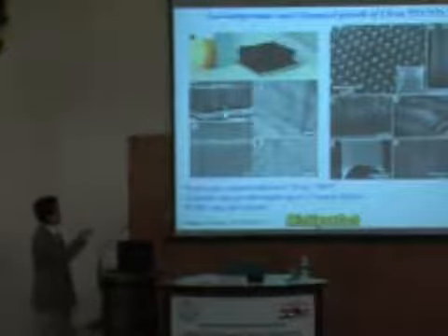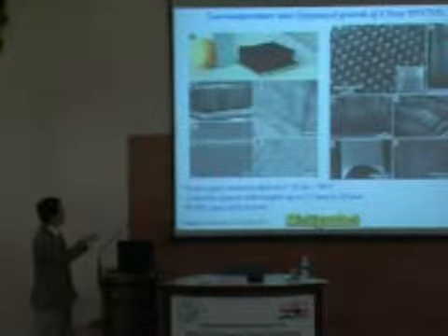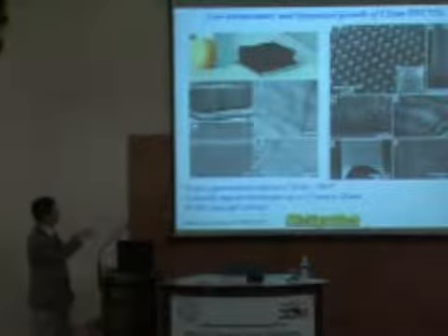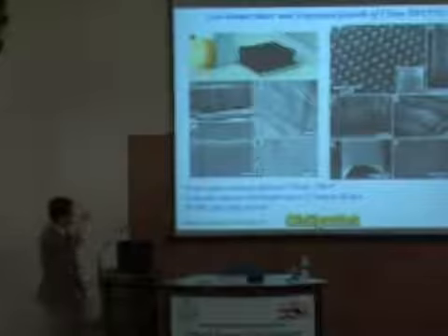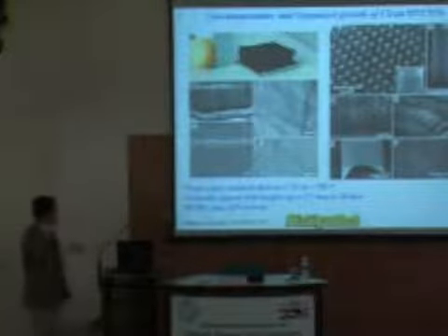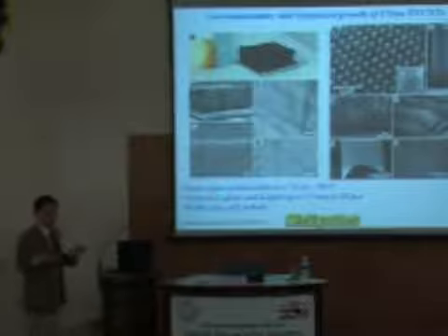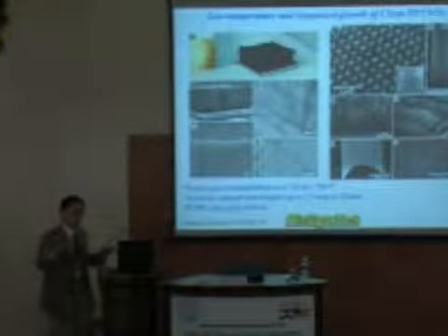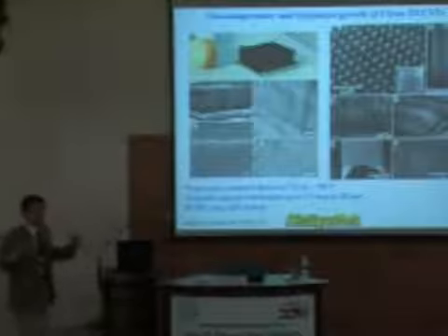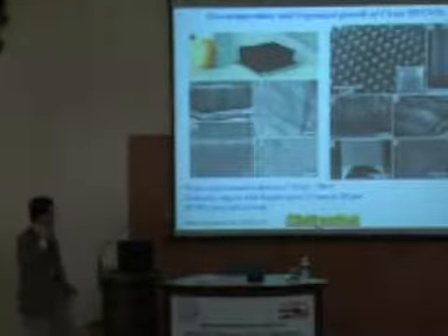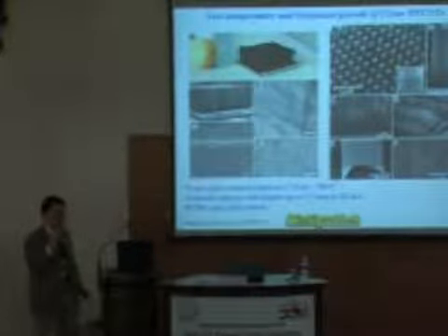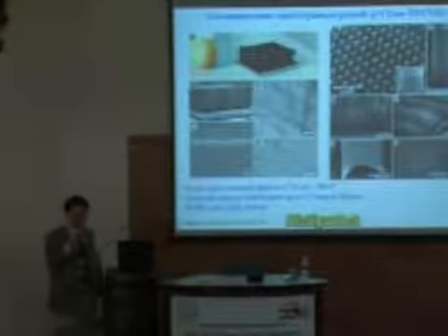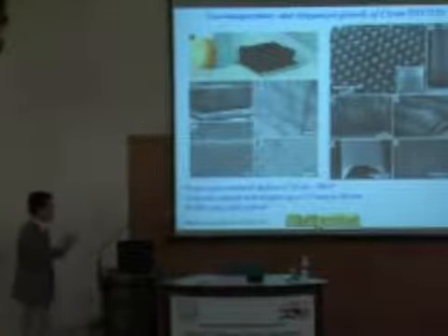And if you zoom in here, the tubes look like this. A whole bundle of the tubes are actually clumped together and become a pillar, right? And this is very important work in the sense that they use water to clean up the catalyst and clean up some of the amorphous carbon so that the tube is nice, clean, and pure. However, if you think carefully, if you're using water to clean the amorphous carbon, there is a chance that you will oxidize your carbon nanotubes at the same time. So you will create defects in your tubes. So this is very exciting work, but it's not the best.